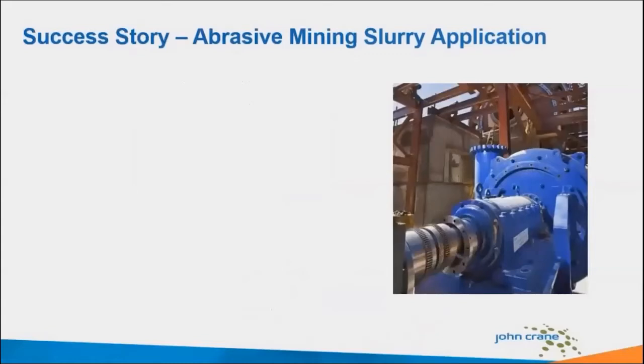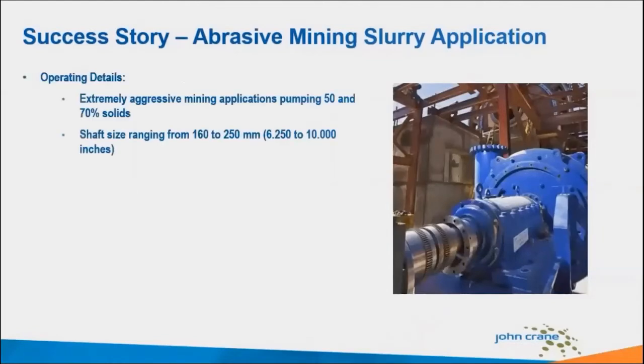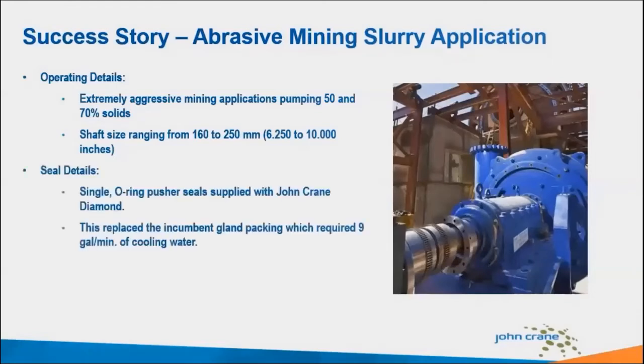The first is an abrasive mining slurry application. The process fluid of this application is an extremely aggressive mining fluid, pumping 50 to 70% solids. And the other thing to note here is that it's on very large pumps with shaft sizes ranging from 160 to 250 millimeters. The seal we provided here is a single O-ring pusher seal supplied with John Crane Diamond on the seal faces, and this replaced the incumbent gland packing, which required 9 gallons a minute of cooling water.